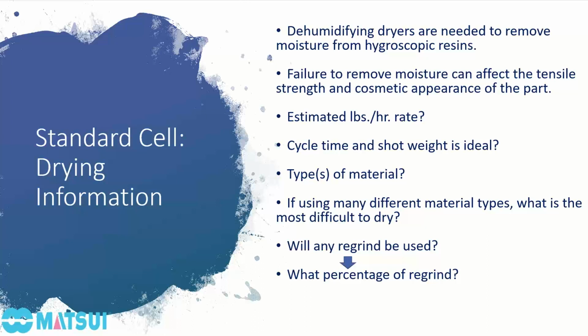what your biggest throughput would be. And the reason the pounds per hour rate is important is there are many different size dryers with different drying hopper capacities based on throughput. You don't want to buy a dryer that's too small, that's not going to keep up with the pounds per hour rate of the injection machine and won't adequately dry material. And you also don't want to buy a dryer that's too big, because it'll just be using too much energy, and also it can run the risk of over drying certain materials. So, coming up with an accurate estimate of what your maximum pounds per hour rate is important.